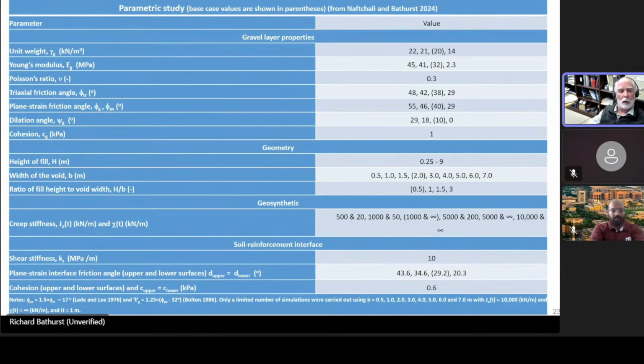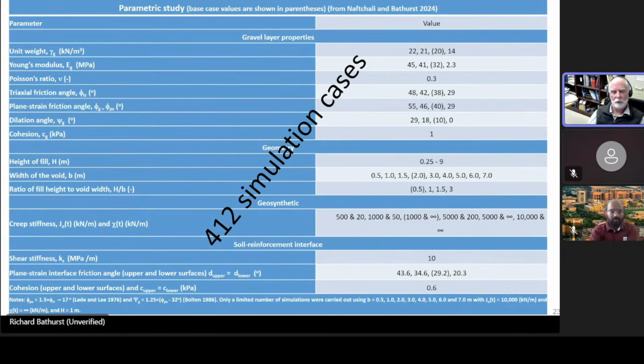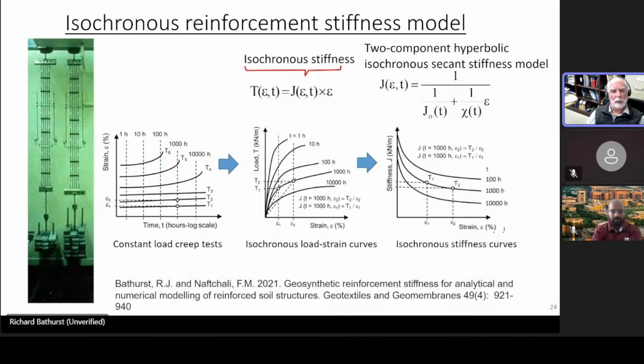And in fact, FAHIMA carried out 412 simulation cases. So it's a huge database of, if you like, synthetic data. And in the simulations, we used our 2-component hyperbolic isochronous secant stiffness model. And this model was implemented in FLAC.